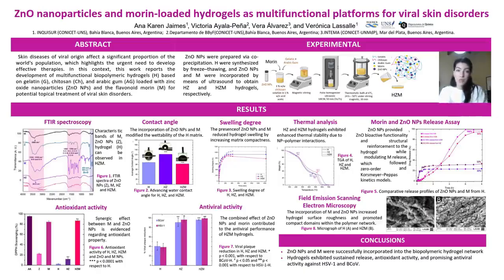This is important because zinc oxide nanoparticles not only provide therapeutic activity, but also improve the structural stability and reinforcement of the material. Regarding therapeutic properties, antioxidant activity was evaluated using the DPPH assay. Hydrogels loaded with zinc oxide nanoparticles and Morin showed significantly enhanced radical scavenging activity compared to the unloaded matrix, whose antioxidant capacity is mainly attributed to chitosan.